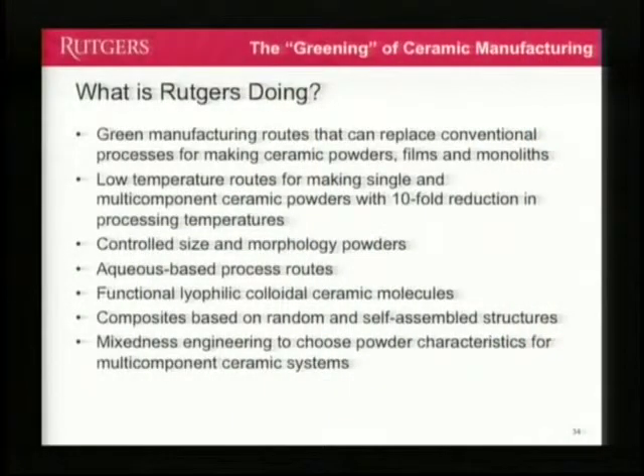Okay, so that aside, what are we actually doing? Well, we're working on techniques that use low temperature processes for making ceramic powders. And we can boast typically tenfold reductions in processing temperatures, and by controlling the size and morphology, we avoid the need for the milling, so we no longer have to grind things. We use water-based routes so that we can recover the water. In fact, we precipitate these things from aqueous solutions, which leaves you with clean water afterwards.